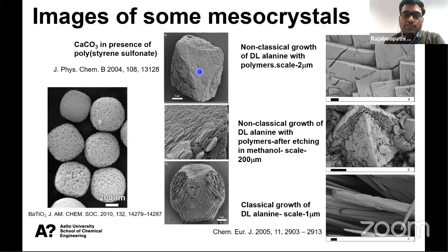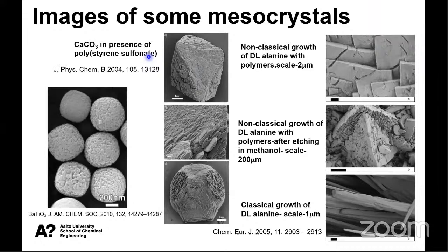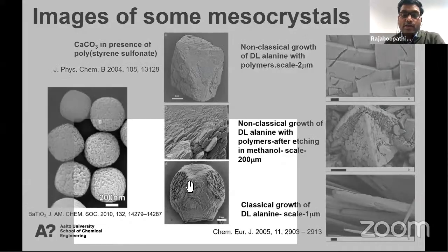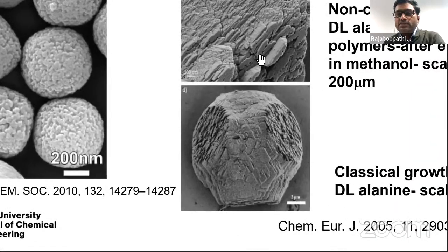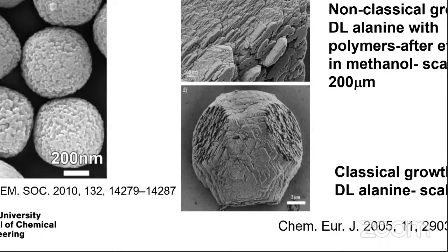And this is calcium carbonate, like nacre, which is a natural mesocrystal. This is a laboratory grown mesocrystal using calcium carbonate. They use polystyrene sulfonate as a polymer to separate the nanoparticle units. And this is a laboratory grown crystal where you can see the surface is not smooth like single crystals. Sometimes it looks like a hierarchical structure, but it always diffracts like a single crystal and only produces a spot pattern.